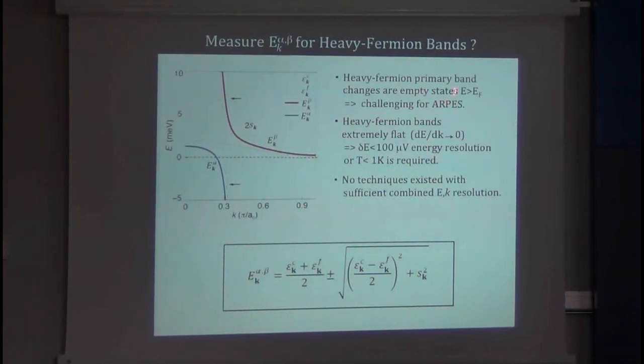Most of this action is above the chemical potential, which is challenging or impossible for photoemission. And furthermore, these things are so flat. That means the momentum changes so rapidly with energy, or the electrons are so massive, that you need energy resolution in the 100 microvolt range or temperatures in the sub-Kelvin range to measure this band structure. And no techniques existed to do this for all those intervening decades from the mid-70s.